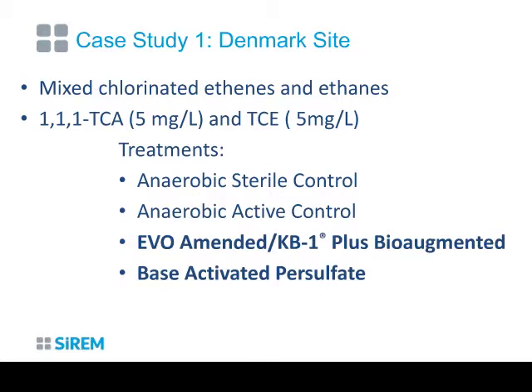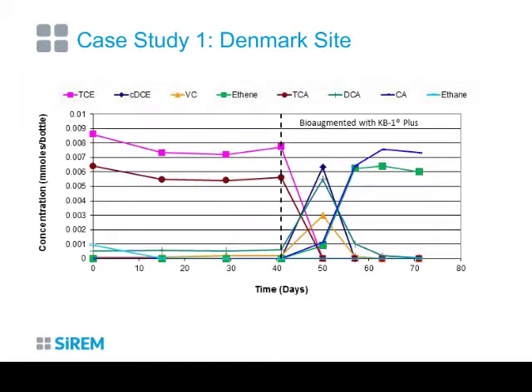So the first treatment that we looked at was emulsified vegetable oil amended and a bioaugmented treatment, and that's EVO for emulsified vegetable oil. And both contaminants were at approximately 5 milligrams per liter in the aqueous phase. So here you see the results presented in millimoles. We've taken the concentration data and looked at the total mass of the contaminant in millimoles per bottle. It allows us to look at mass conversion. In bioremediation applications, you can actually see really good mass conversion, so it's a nice way to visualize the data. TCE is in the bright pink color. 1,1,1-TCA is in sort of the reddish-brown color.